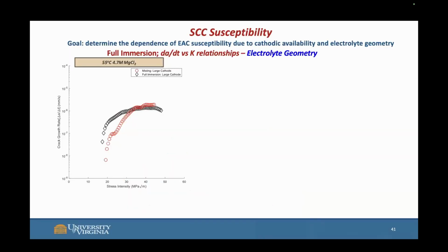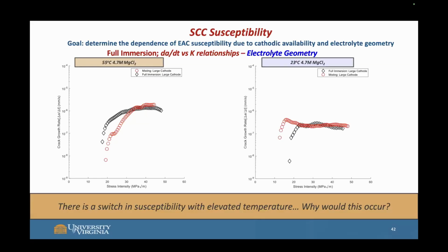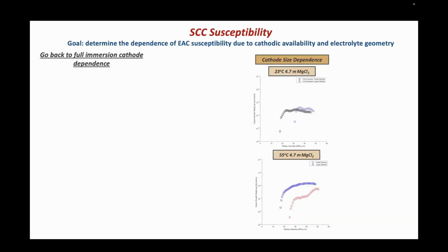So what happens at 55C? Well, we did a test and we actually found that at 55C, so this is crack growth rate versus stress intensity, full immersion is actually more susceptible than the misting conditions, which is the exact opposite of what we saw at room temperature. So why could this possibly occur?